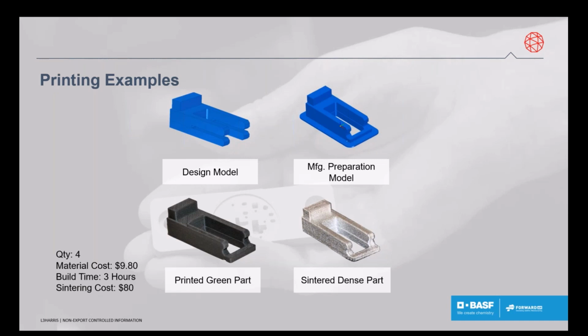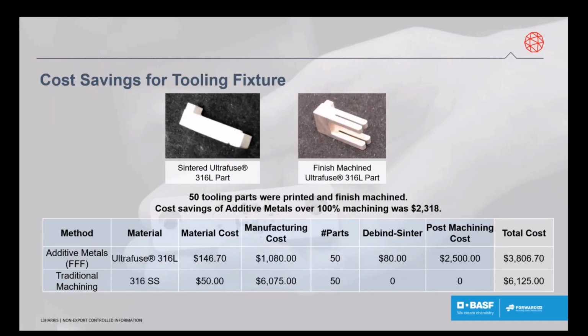Material cost for this, for a quantity of 4, was $10, and 3 hours to build them, and $80 again for sintering. And this is the final version of this same part, and we increased the bridge size across the end, and we added machining material to the bottom of the part, because we found that the bottom surface had to be extremely polished, highly polished, because this slides on a circuit board.